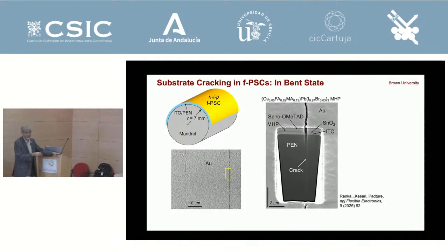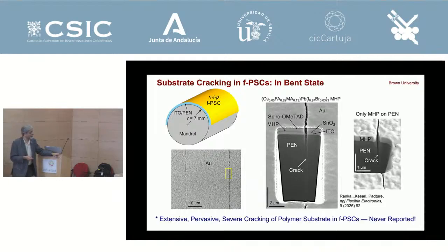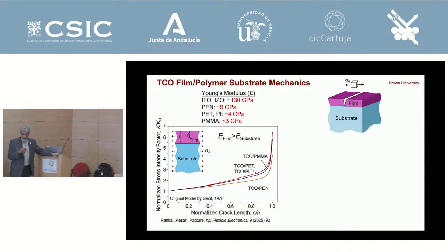And it's also cracked. So a lot of people publish this work, figures like this, saying, okay, this cracks, therefore everything is brittle, so everything cracks. But nobody says anything about whether the ductile substrate cracks, and it does crack. And if you put perovskite just on the PEN without any layers, even that makes the polymer crack. So it's really fascinating. Anyway, we found a paper from 1978. It's a modeling paper, nothing to do with solar cells. And all it said is that when you have a stiff film on a compliant substrate, then when the crack approaches the interface, the stress intensity factor goes to infinity. There's a singularity because of the stiffness of the film. That's the only difference.